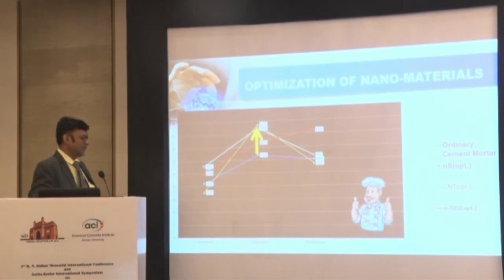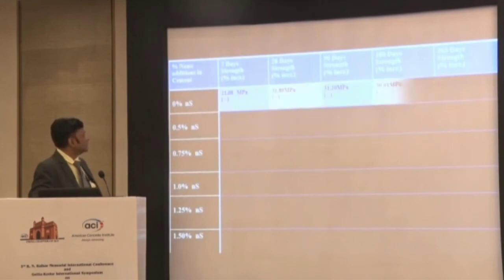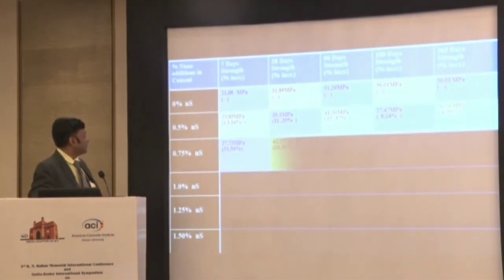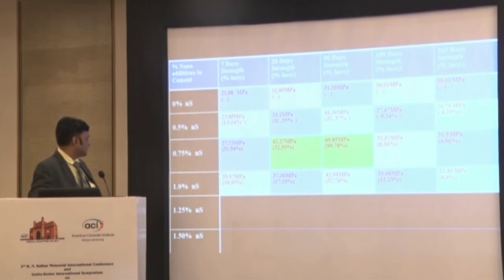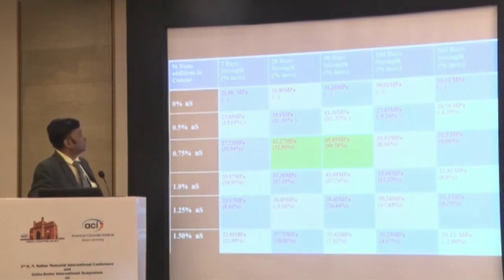I have got optimization at nanosilica 0.75% with respect to cement, carbon nanotubes 0.02% with respect to cement, and nanotitanium dioxide at 1% with respect to cement. These are verified by many literature reviews and authors, but there is also wide variation in optimizing dosages. These are my results for 0%, 0.5% nanosilica, 0.75%, 1%, 1.25%, 1.5%. I am getting a 32.55% increase at 28 days, which is my optimization.